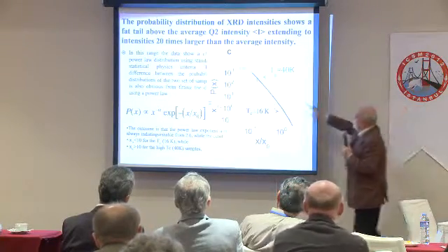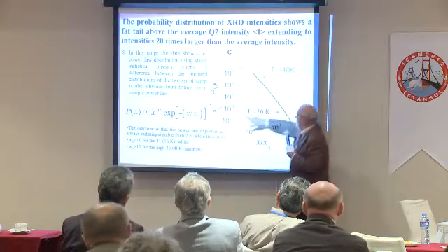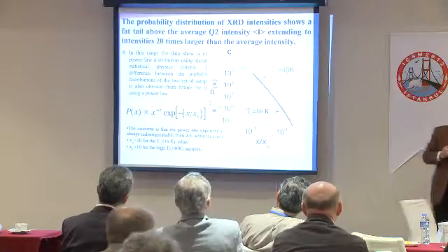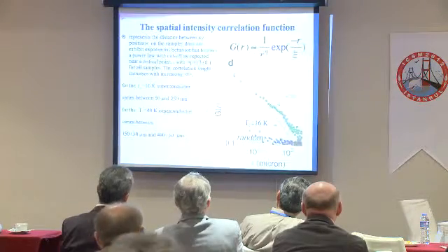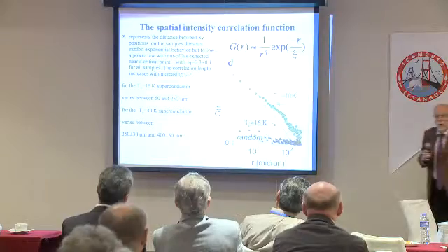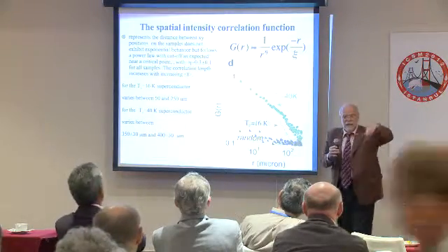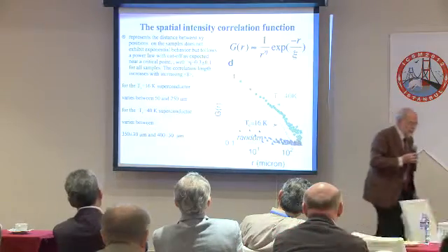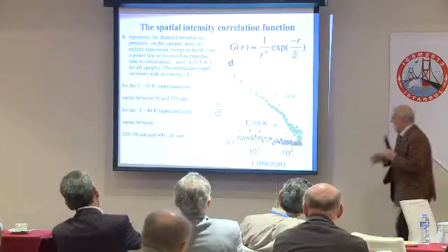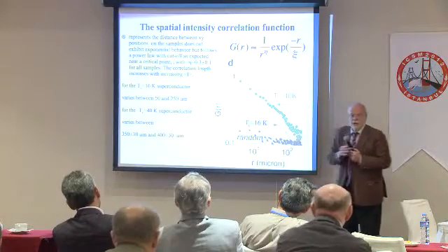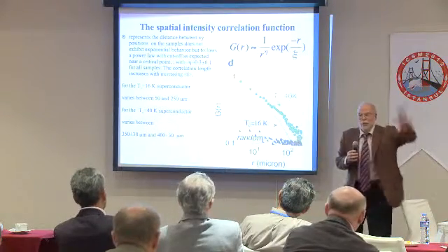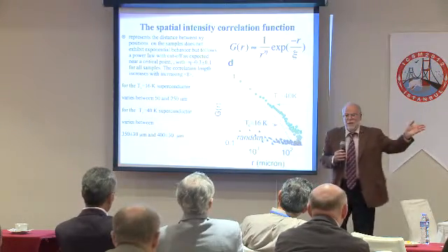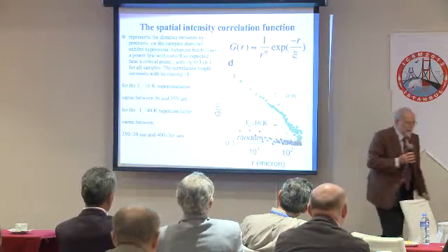Then you can normalize the two. You see the cutoff is very large, it's normalized to the cutoff. And when it's not a power law, this goes down. Also with the correlation function, you can see that a patch of ordered oxygen is correlated with another one. We can characterize this, and you can see that you can reach up to 100 micron correlation length. If you go to the other section nearby, exactly in parallel to that, you will see a granular superconductor, so you can see cases where this can happen.